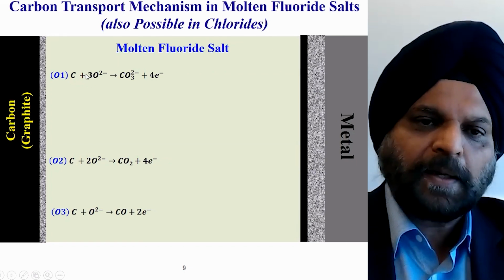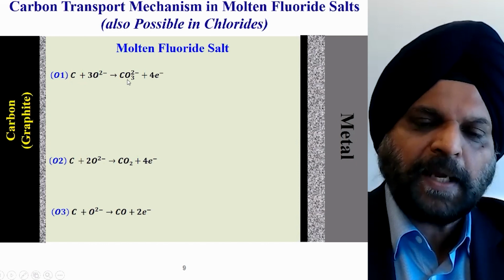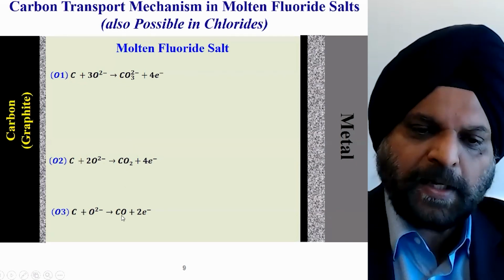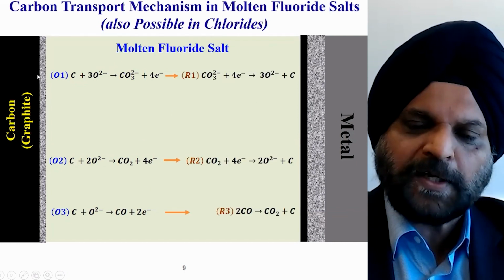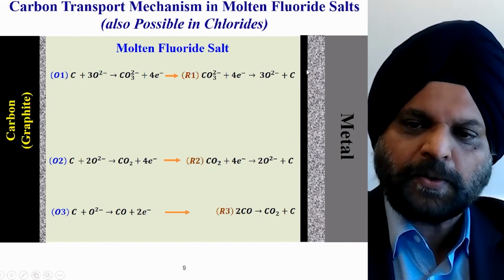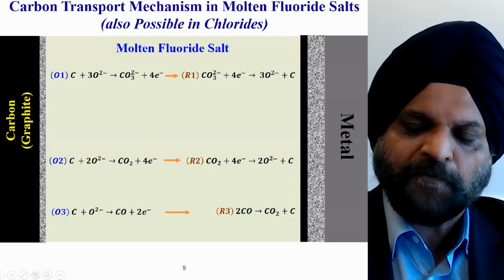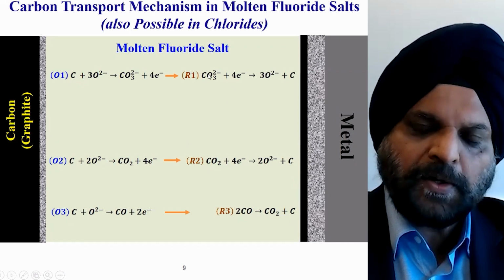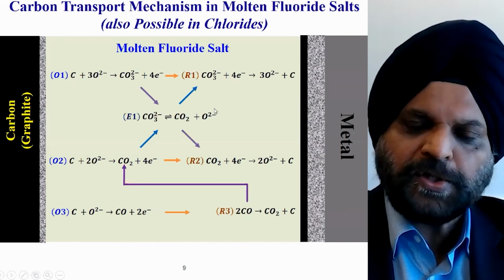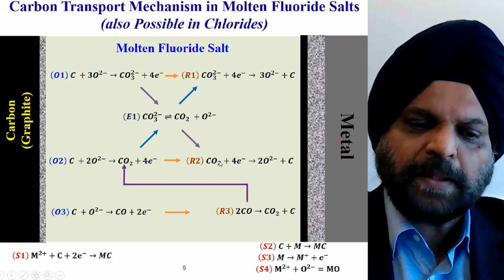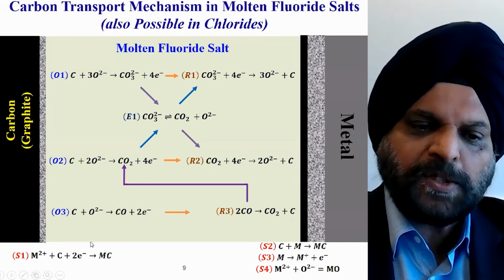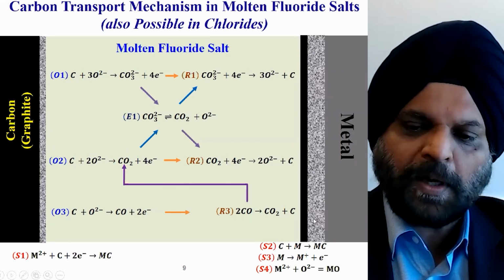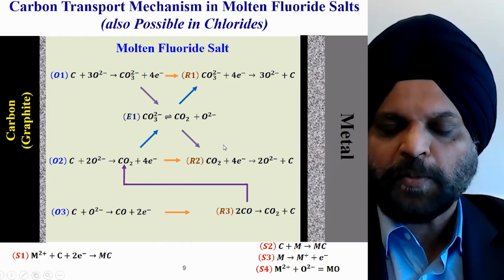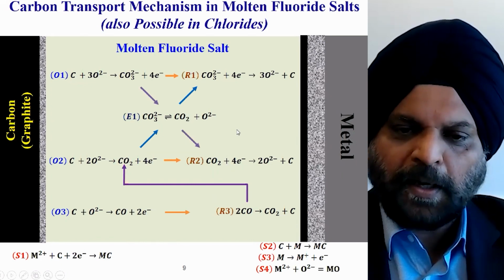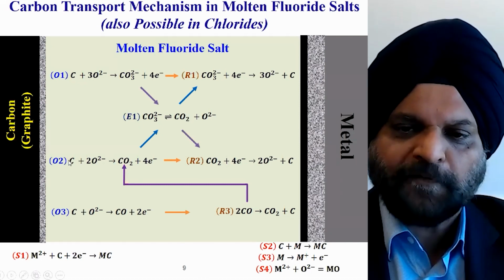For example, here, these oxides can form not just carbonate, but there can be other constituents like carbon dioxide or carbon monoxide. And they will transport carbon from the graphite surface through molten fluoride to the metal surface because of their driving force, where carbides can form on the surface here. Carbon monoxide or carbon dioxide or carbonate, they can actually convert depending upon oxidation potential and oxide concentrations. But the main thing is that on the metal surface, you can transport carbon, which is this metal may be totally away from graphite or electrically totally isolated, but through fluoride salts, this carbonate formation or carbon dioxide or carbon monoxide formation can lead to transportation of carbon from the graphite surface to the metal surface.